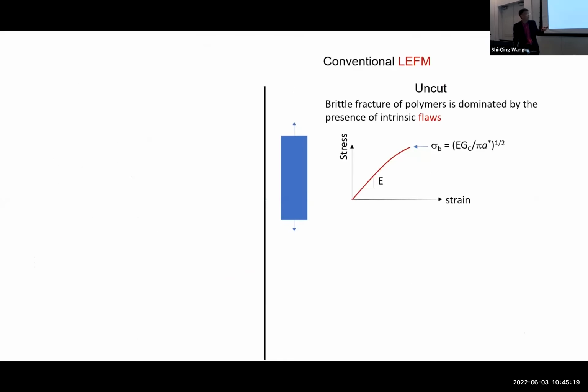So if I review it for you again, fracture mechanics told us for our polymers, window glass definitely is flaw intolerant. In other words, it cannot tolerate flaws. But does this really work for our polymers? Well, the framework of linear elastic fracture mechanics is to say, give me an uncut sample. The way I understand the fracture strength is because there are flaws. Period. And how do I estimate this? I better get GC. How do I get GC? I use a cut.